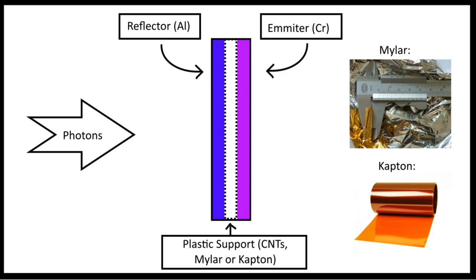Metals such as chromium provide high emissivity on the back side of the sail, while aluminum is used for the reflective side. This emissivity is integral to the solar sail since it is temperature dependent and will need to be monitored and regulated when in close proximity to a star. Using these materials, solar sails are made by depositing thin films about 100 nanometers thick. These films are then laid out, bonded together, and finally structurally reinforced into the sail membrane.